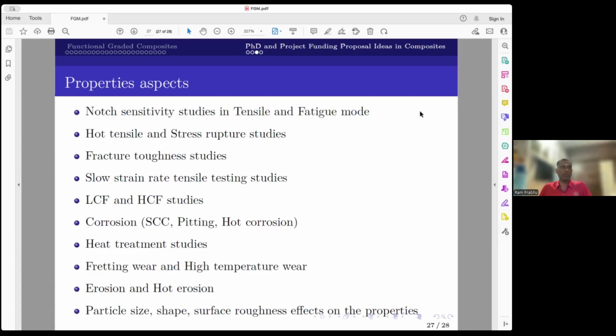All of you do in polymer composites or the metal composites just a simple tensile testing in the sheet or round samples. But if you introduce the notch with a different radius of curvature, the kind of stress concentration you introduce will vary, resulting into different mechanical properties. In fact, it changes your fracture behavior, like a ductile to brittle. This data will be very, very much essential for the designers in designing any kind of structure.